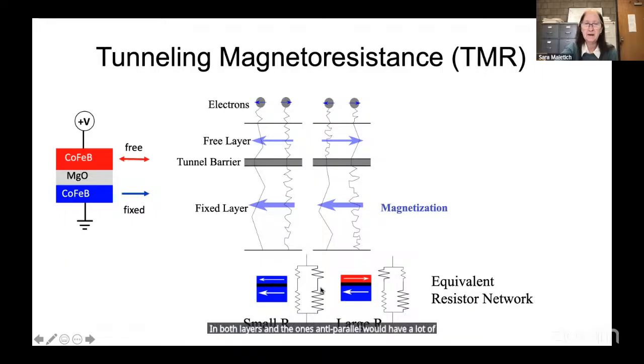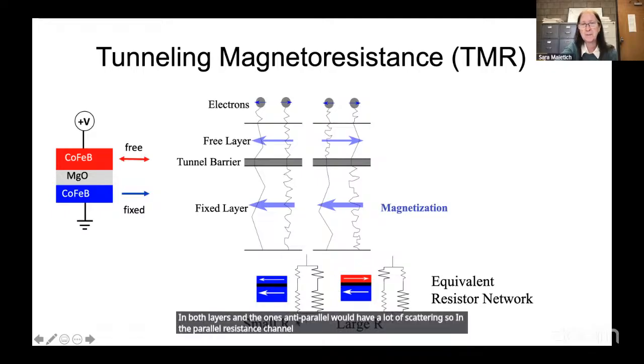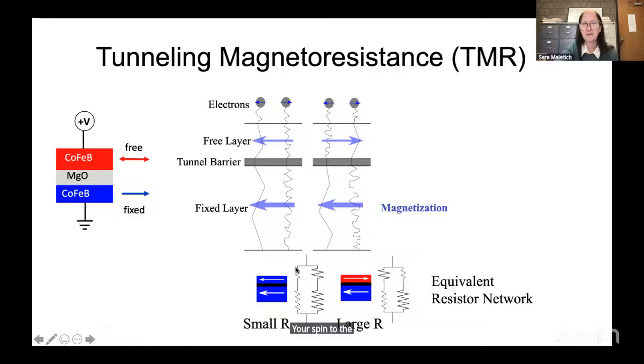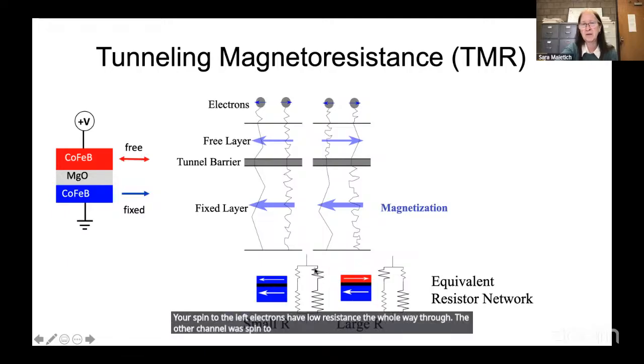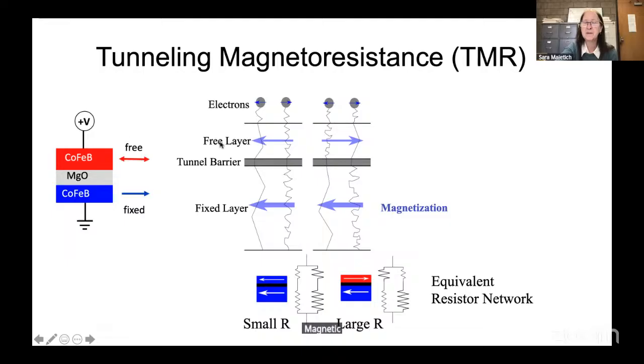So in the parallel resistance channel models, your spin to the left electrons have low resistance the whole way through. The other channel with spin to the right has high resistance, and so the tunnel current is going to shunt through the low resistance path. And overall, you get a smaller resistance than if you have anti-parallel magnetic orientations in the layers.